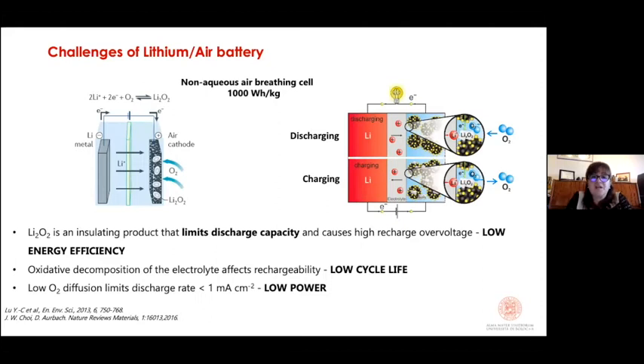Which are the challenges of lithium-air batteries? Lithium-air batteries are promising very, very high practical specific energy, as I told you, 1,000 watt-hour per kilogram. And the classical configuration of this kind of batteries is an air-breathing cell, where you have a lithium metal and electrolytes, and typically porous carbon or porous electrodes, where oxygen reduction takes place. It is exposed to air.